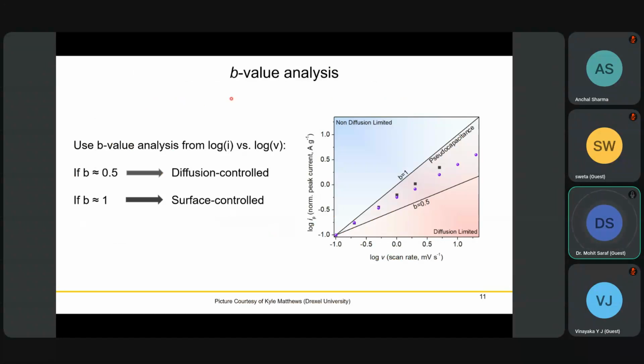This process is called B value analysis, given by Professor Dunn. You plot the log of scan rate versus the log of peak current, and you get a graph. If the value of B comes out to 1, then it is a surface controlled process, and you are in the supercapacitor regime. But if the process gives you a B value of 0.5, then it is a diffusion limited process, diffusion controlled process, so you are in the battery regime. In between, you have mixed behavior with both surface and diffusion controlled contributions.